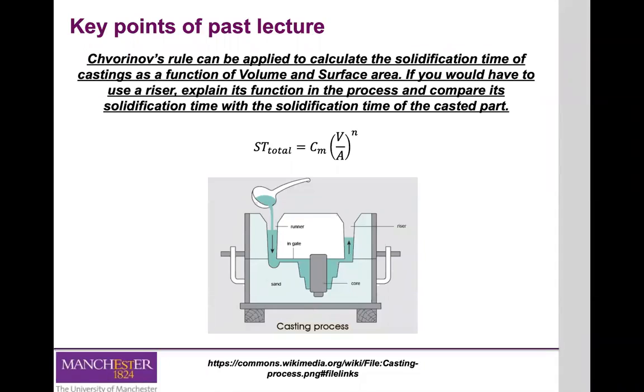Another important point from the previous lecture is Chvorinov's rule. We can use this rule to calculate the time it takes for a material to solidify within the molds and form a part. The solidification time depends both on the volume of your part and on the surface area. The higher the surface area, the more area available to exchange heat with the ambient, the higher the heat exchange rate, and therefore the smaller the solidification time.